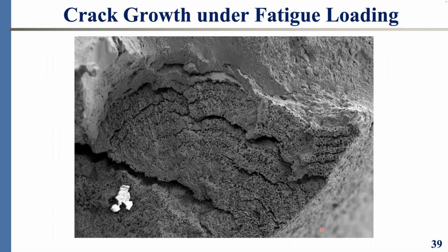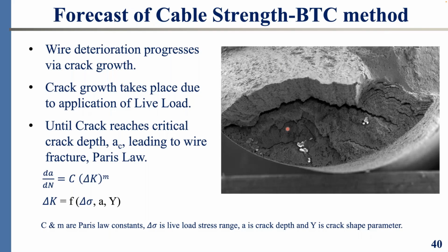Now, going towards the mother of all tasks, which is the forecast of life. We talk about crack growth under the fatigue loads, and in terms of that, we see this crack. I can tell you that the day we took this bridge wire out of the bridge cable, identified the number of years that this depth of crack survived the fatigue loads. And of course, we know the parameters. This is done with statistical work, and we have a subroutine to quantify the fatigue crack growth.